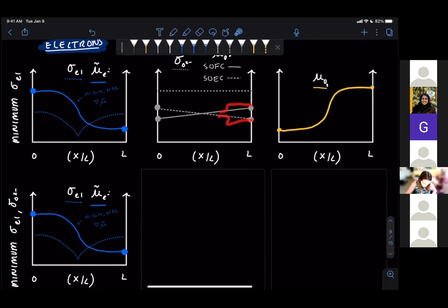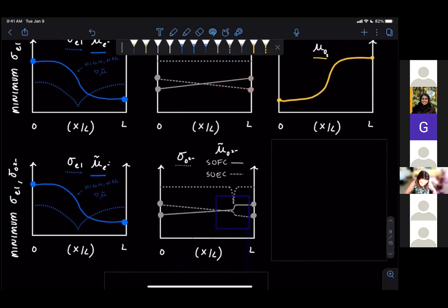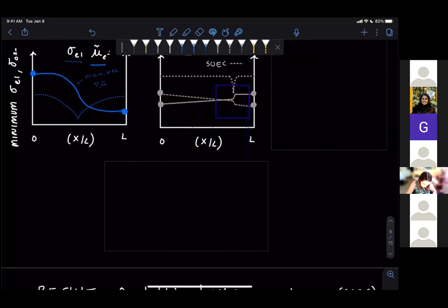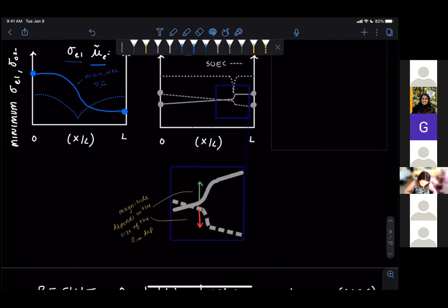And so I'm not going to try to draw that for you on the spot. I'm smarter than that. But it's essentially going to look like this. For this localized dip in the ionic conductivity, for a fuel cell, you see this sharp increase, and this is going to be for our electrolyzer cell. It's again a sharp increase, but in the negative direction because it's going to be a negative potential profile. And just zooming in on what that looks like, I drew it rather small.